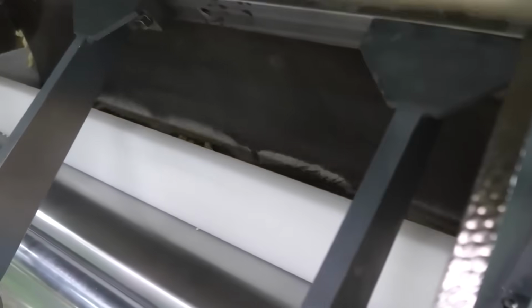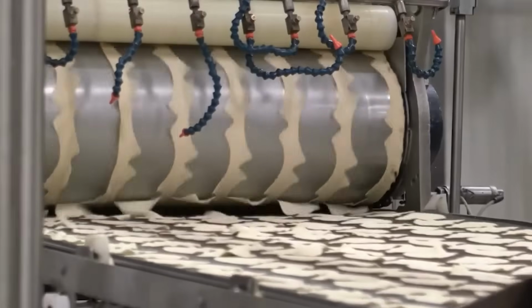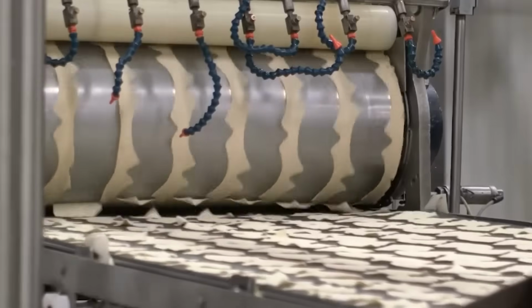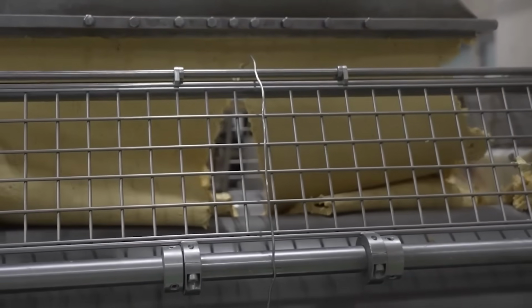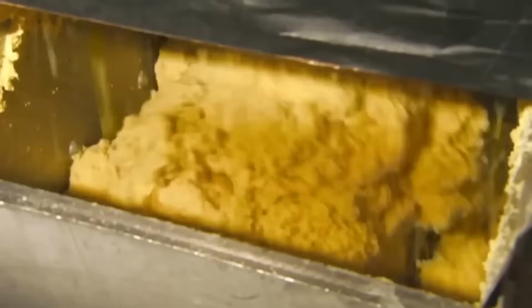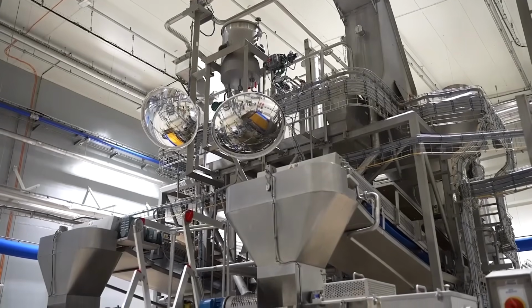Ideal masa temperature coming off the stones is around 45 to 55 degrees Celsius. Viscosity is checked using inline sensors that measure flow resistance, and if adjustments are needed, small amounts of water or dry masa are mixed back in using an automated feedback loop. Now it's time to form the masa into flat sheets. The ground masa is transported via auger screws into a sheeting machine, which extrudes the dough between two polished stainless steel rollers. These rollers are adjustable to control sheet thickness down to the millimeter, usually targeting between 1.2 and 1.8 mm, depending on the final chip specification.